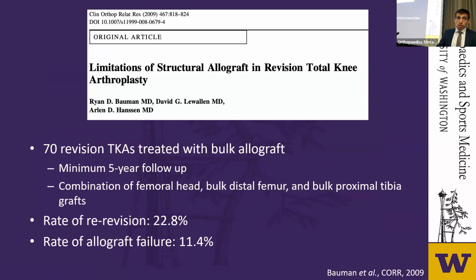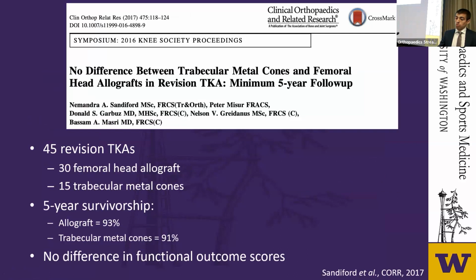The literature out there on bulk allograft hasn't been as clear as it has been for some of our other strategies for bone loss. To illustrate that, first, this 2009 study published in CORR looked at 70 revision knees treated with a variety of different forms of bulk allograft, both femoral head, distal femur, and proximal tibia bulk grafts. And they found over 22% rate of revision in that population, half of which was due to failure of the allograft itself. So these authors concluded that they were not happy with the success rate that they were seeing with bulk allograft and advised against its routine use.